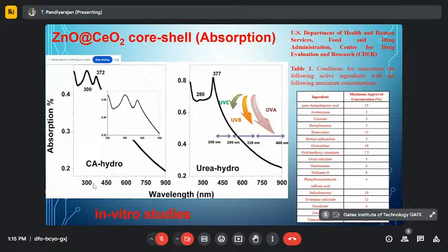Because if you look at the absorption spectra, it has an absorption range from around 250 to 400 nanometer, right? So this exactly matches your requirement of capturing ultraviolet B to ultraviolet A, right? So that is why we have used zinc oxide and cerium oxide as a core-shell material for effective utilization in sunscreen products.